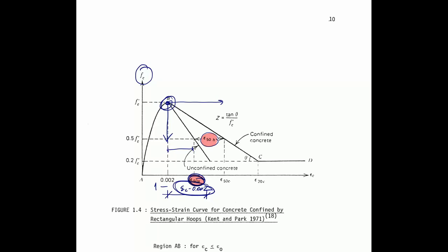And the material model is the Mohr-Coulomb, okay, for the brittle one. The thing is that when you compress the material, you don't get the compression failure in reality. To be precise, it is not the compression failure, okay. The failure plane occurs in the maximum principal tensile strain.